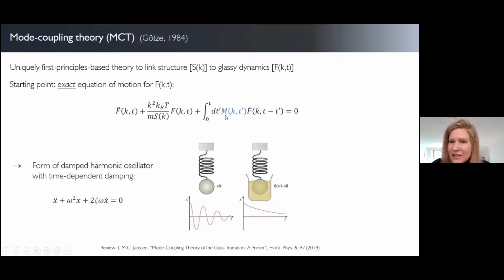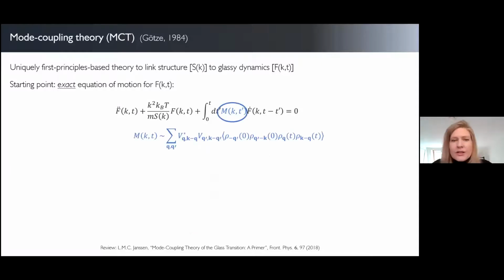If we would know that, we would be able to solve this equation rigorously. Now, it turns out to leading order, this memory function can be written as a more complicated object that now contains a correlation function over 4 different density modes. So it probes correlations between 1, 2, 3, 4 different density modes at 4 different wave vectors and between time 0 and any time t.